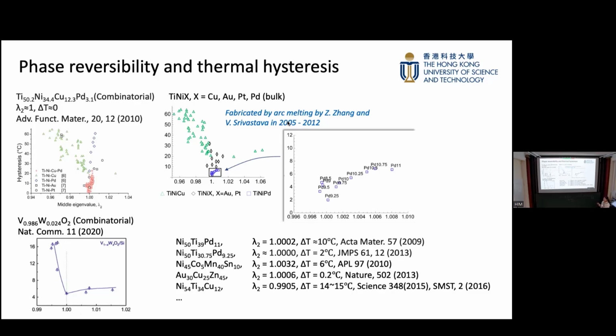It means that if the phase transformation type is different, the thermal hysteresis minimum corresponds to a different degree. So for example, here it can really reach 2 degrees, but in this material it can only reach 6. And for some of the samples here, it can really reach 0. And for some of the materials, you tune the material and try to find the minimal hysteresis by making lambda 2 equal to 1, but the minimal hysteresis may be two digits.